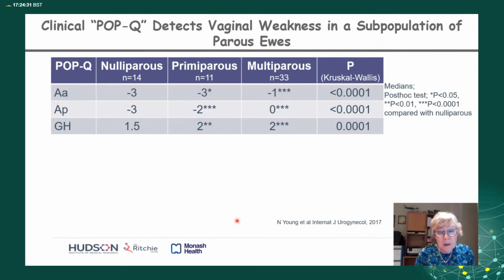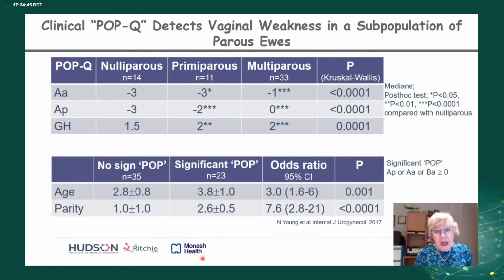These are just some of the POP-Q points that we looked at. But the Aa and the Ap point, you can see as the parity of the sheep increased, these worsened quite significantly, and similarly for the genital hiatus. Now, we also noticed that the parous sheep seem to be in two groups, really: normal POP-Qs and abnormal. And so what we did is we separated them on the basis of abnormal being an Ap, Aa or Ba greater than or equal to 0.